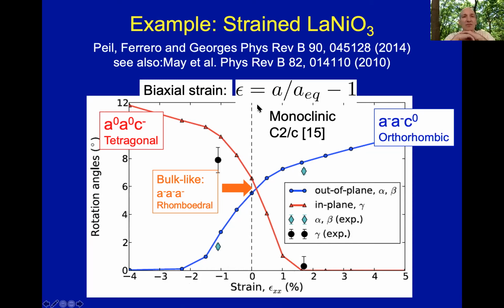So this illustrates the fact that strain is an important control parameter, not only to change the distance between atoms and hence the overlap of their wave functions and the bandwidth, but the story is actually more complicated because the angles change and you can make certain bonds more straight and certain other bonds less straight, depending on the sign of the strain that you apply. And all this has interesting consequences for the electronic properties of the material.